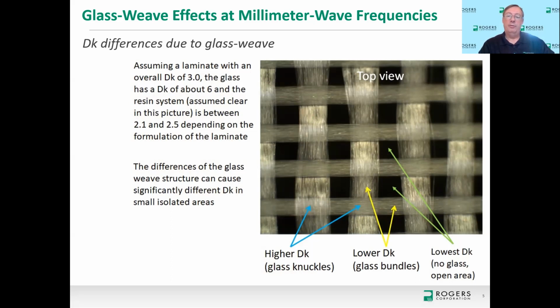And if you were able to do a very discrete measurement for dielectric constant at the tips of each one of the arrows I'm pointing to in this picture, what you'd find is the blue arrows are pointing to areas that I'm calling glass knuckles. And in these areas, you have glass bundles that intersect each other. So you really have two layers of glass.